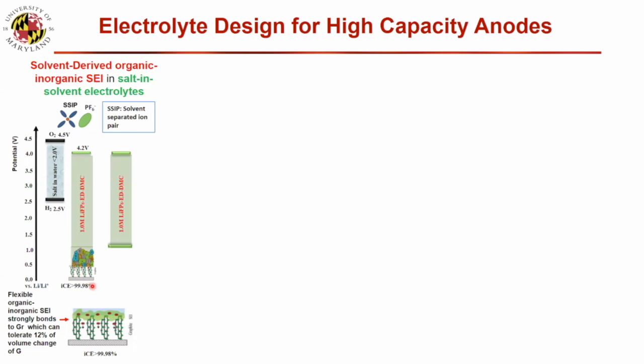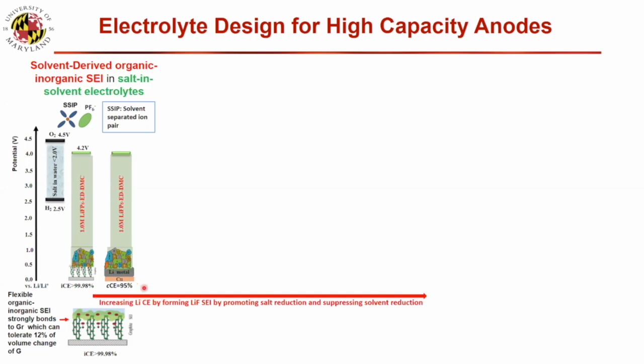But if we want to increase the capacity and use silicon or lithium to replace graphite, then with the same electrolytes, they also form the same SEI. But since this organic-inorganic SEI is also strongly bonded with the lithium metal, and the lithium metal has a huge volume change during plating and stripping, if the bonding is really strong, the SEI also suffers similar volume change. Then during many repeated volume changes, they will crack. When they crack, they self-heal and reduce the Coulombic efficiency to 95 percent. That will limit the cycle life. So the goal is, how can we change the electrolytes to make this number higher, at least above 99.9?